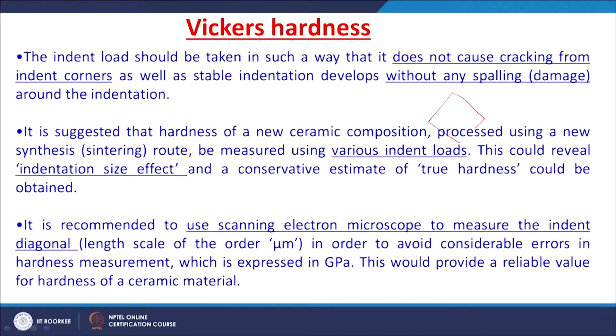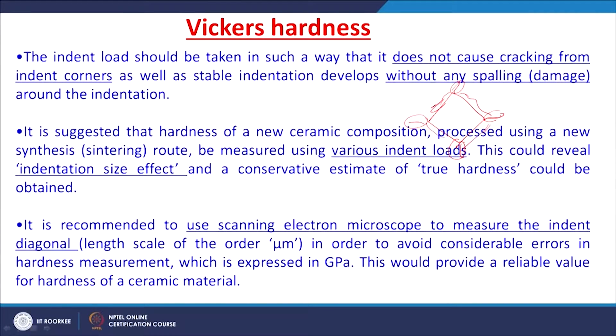Vickers indentation must be done very carefully to obtain the hardness of the ceramic material. The indent load should be selected such that it does not cause cracking from the indent corners and does not give any spalling or damage around the indentation. We will select a load where there are no cracks generated from the corners and no damage around the indentation. It is also suggested that the hardness of a new ceramic composition processed using a new synthesis or sintering route be measured using various indent loads.